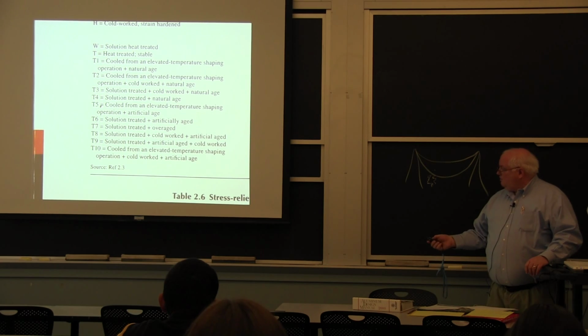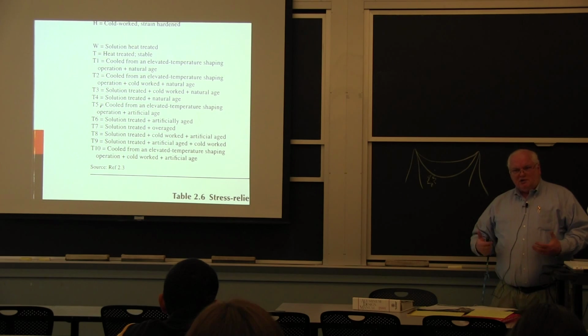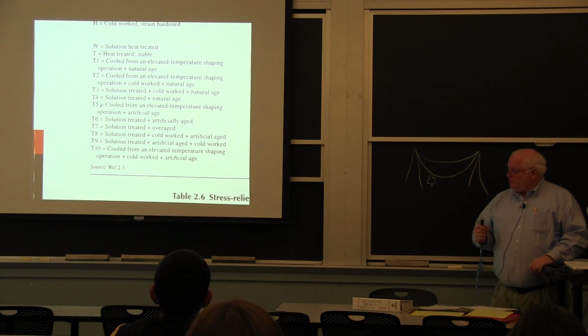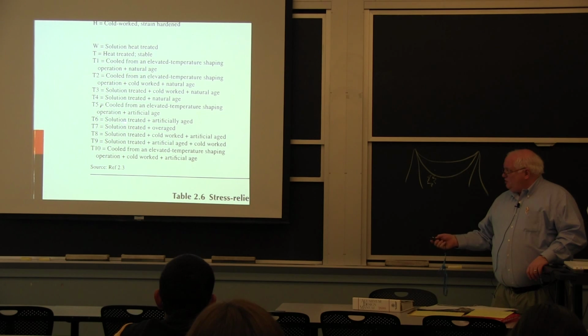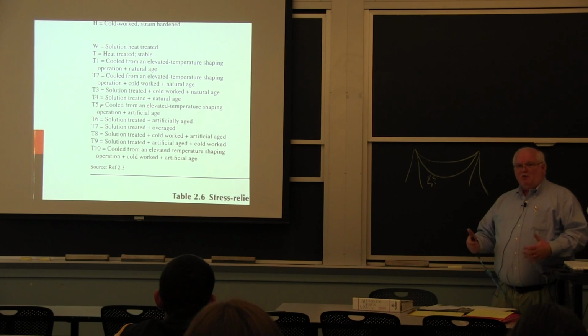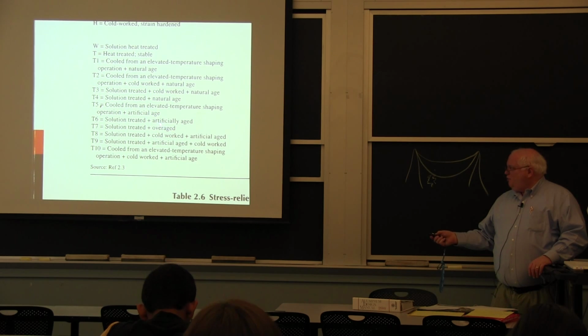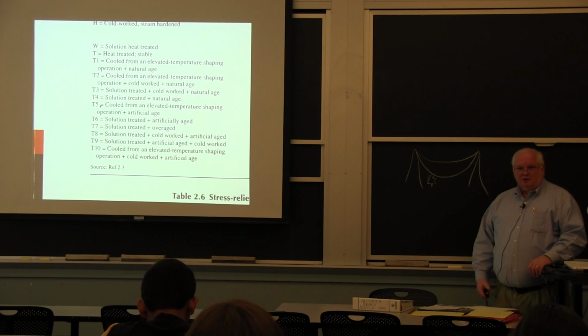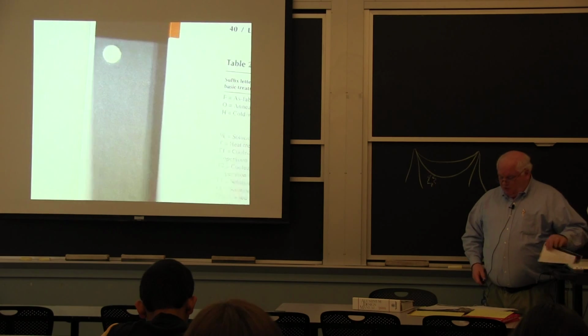Other things might be T3, which is solution treated, cold worked, naturally aged. There's all kinds of combinations. There's T6, which is solution treated and artificially aged. You put it in a furnace at a certain temperature, and you try to get the maximum strength. T7 is solution treated and overaged. Why would you overage to not get the maximum strength? Because you get like triple the stress corrosion cracking resistance in a T7 that you get in a T6. Okay, if you take some of my other modules, I'll talk about some of those things.